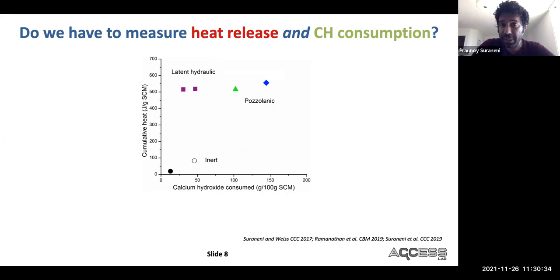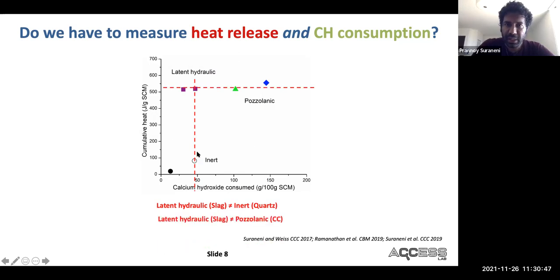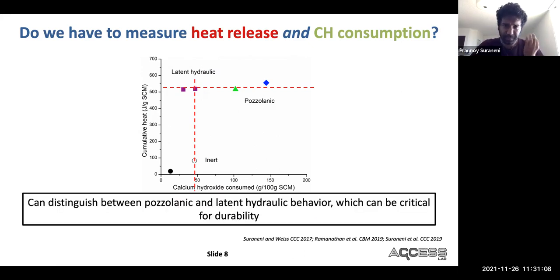So the reason we do measure both heat release and calcium hydroxide consumption: if you use only the calcium hydroxide consumption, you can get very similar values with a latent hydraulic material and an inert material. If you measure only the heat release, you can get very similar values with the latent hydraulic material and a pozzolanic material. But if you measure both of these parameters, there is absolutely no doubt which material is where. So to properly classify, to differentiate between the slag, the quartz, and the calcined clays, you have to measure both. This is the only way that you can actually distinguish pozzolanic and latent hydraulic behavior, which, of course, as we've mentioned, is critical for concrete durability.